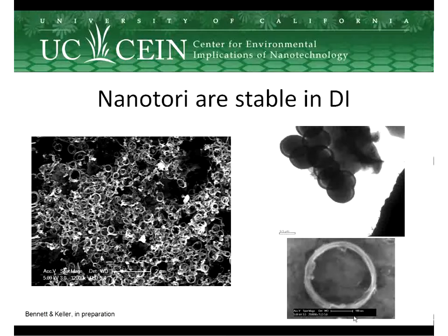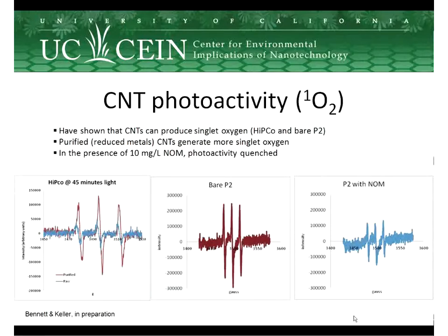I think we went with toluene just because it's a non-carcinogen, so we thought it'd be easier to work with. But it could be that just the aromatic ring works. We're thinking that the interaction is between the carbon nanotube and the aromatic ring, and the pi-pi interactions are really basically helping it to get into the suspension. That's our theory, and we're sticking with it.